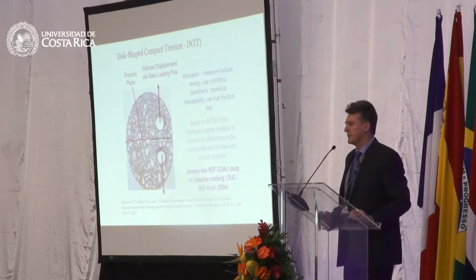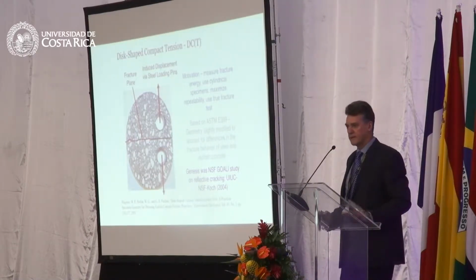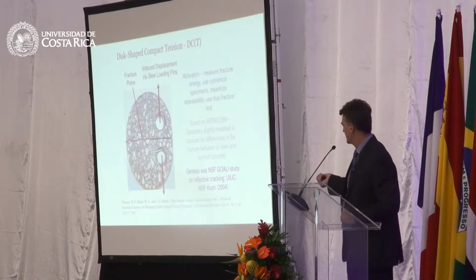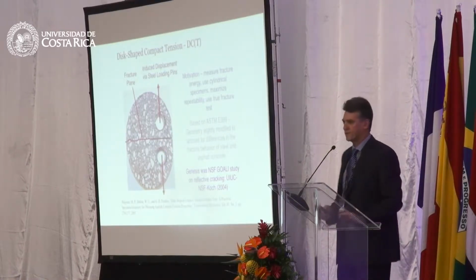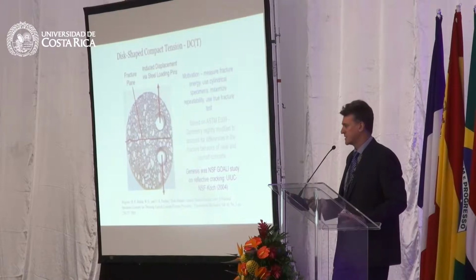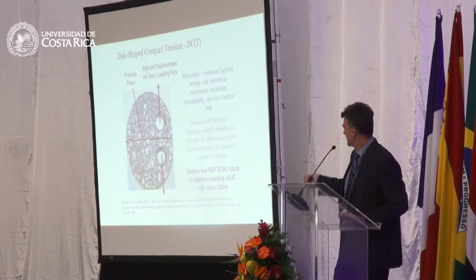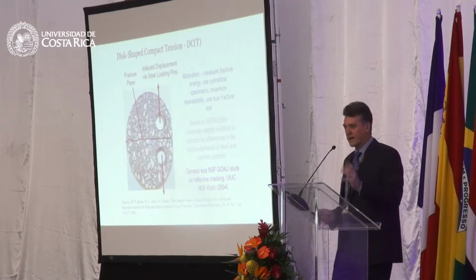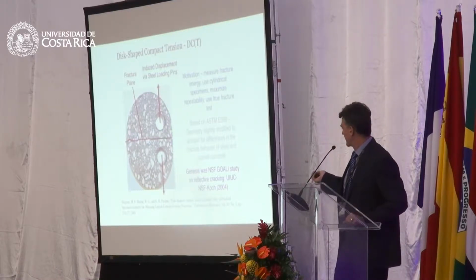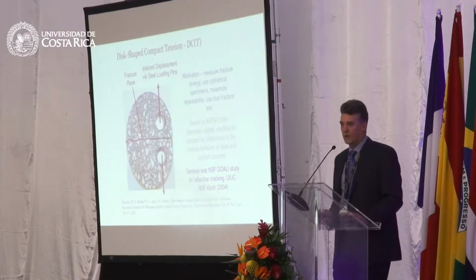We wanted to develop a test in a cylindrical shape, and we wanted it to be practitioner friendly but accurate enough for research. A geometry that had been used in other fields was a disc-shaped compact tension fracture, so we modified what we found in the ASTM specification for other materials to work for asphalt.